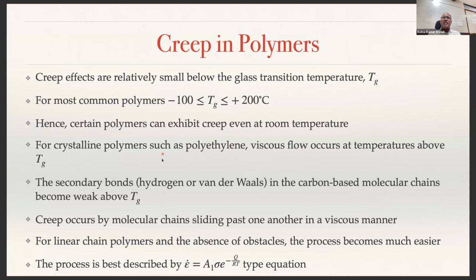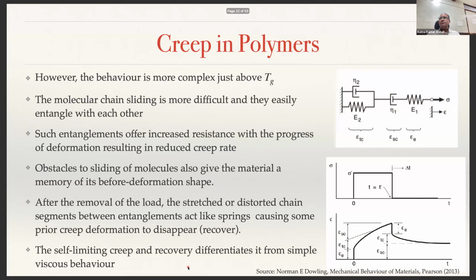For a crystalline polymer such as polyethylene, viscous flow occurs at temperatures just above Tg, that means their glass transition temperature. What happens when you operate above Tg? The weak secondary bonds or van der Waals forces in carbon-based molecular chains such as polyethylene become weaker above the glass transition temperature, and that causes the permanent deformation. Again, this process can also be described by a similar Arrhenius type equation: epsilon dot is equal to A1 sigma e power minus Q by RT. That means epsilon dot represents the strain rate as a function of time.